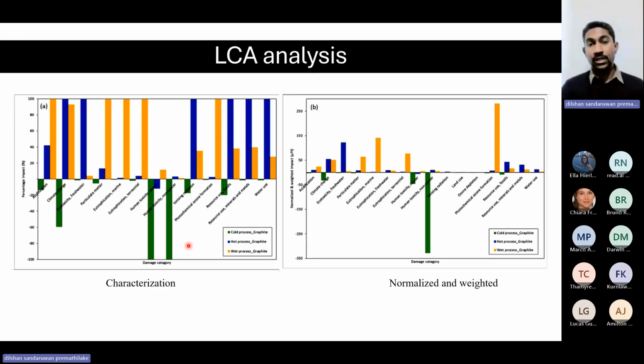And then I tried to do a life cycle assessment, the environmental life cycle assessment first, to understand which process performed the best in recovering graphite. So here you can see that the cold process derived graphite is going to give us a negative impact. This is due to the large amount of copper that I can recycle along with the graphite. Which means if I'm going to recover copper from this method, it can reduce the amount of copper that is going to be extracted through mining. So this is based on the avoided products. I'm going to have a negative impact for the physical process or the cold process. However, the quality of the graphite is questionable, because the quality of the graphite is going to be quite low in this method.